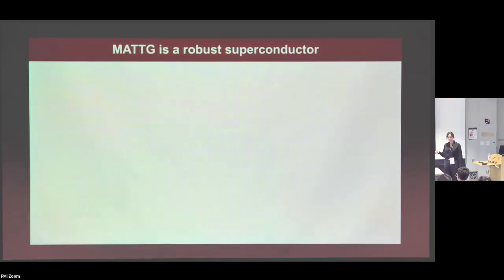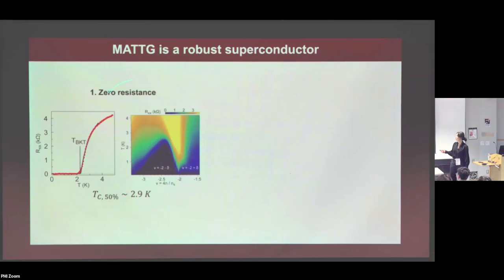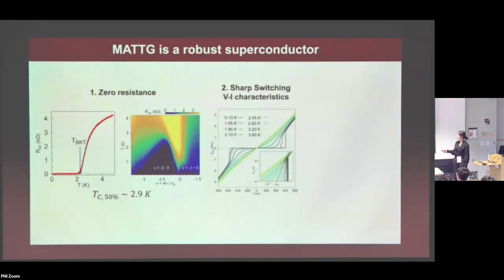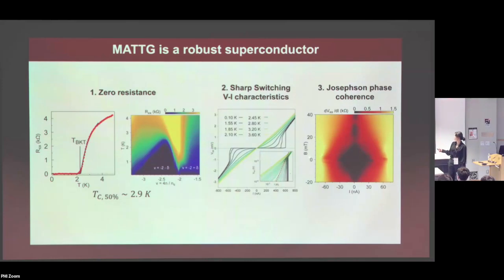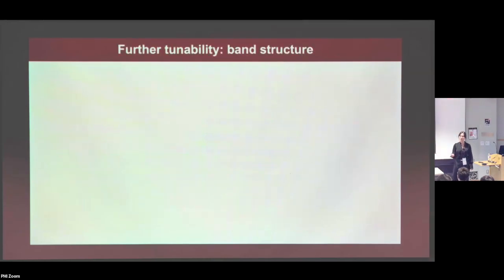We experimentally realized this system, and we found absolute zero resistance in this temperature dependence measurement, as well as sharply switching IV curves. Also, when we apply a small out-of-plane magnetic field, you see these oscillatory patterns, called Fraunhofer patterns. Honestly, only when you have the combination of all three can you claim that your superconductivity is a real two-dimensional superconductor. So we found another system that is another Moiré superconductor. That's already kind of cool, but that's not it, because we wanted to answer more questions than just that.